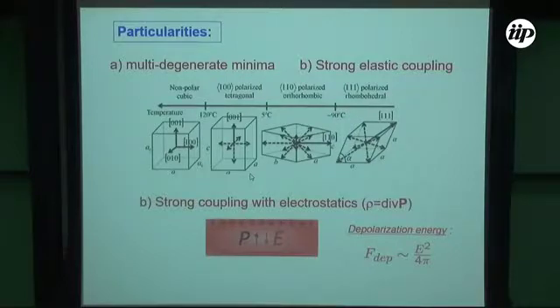This is called depolarization field, and this is exactly the origin of this coupling of polarization with electrostatics. The depolarization energy due to this field is very huge, and it creates the so-called depolarization paradox, because when properly calculated, the energy appears much larger than the energy of condensation of the polar state. And in principle, strictly speaking, the ferroelectric cannot exist. So this depolarization paradox was noticed a long time ago, and I will speak a little bit further about it.